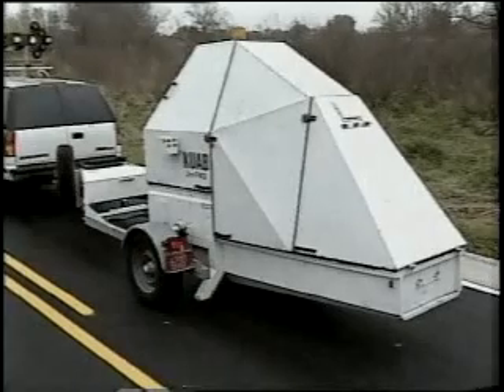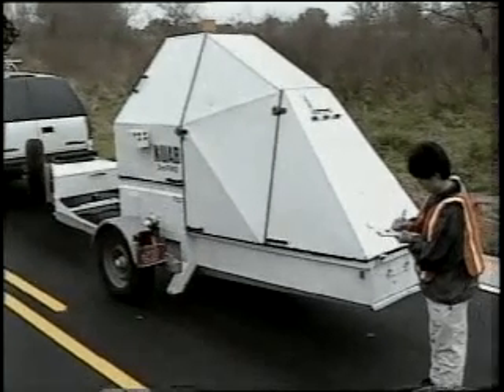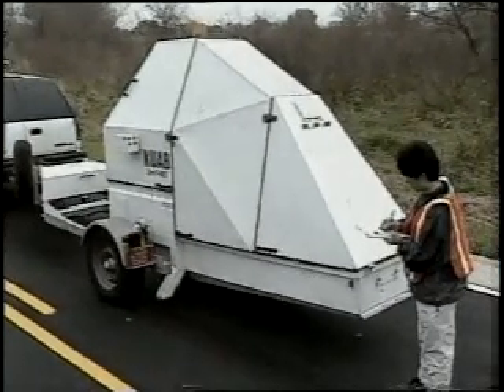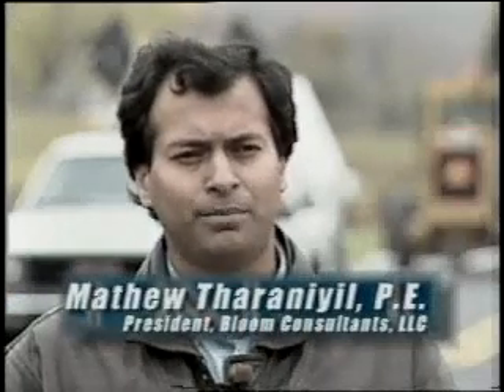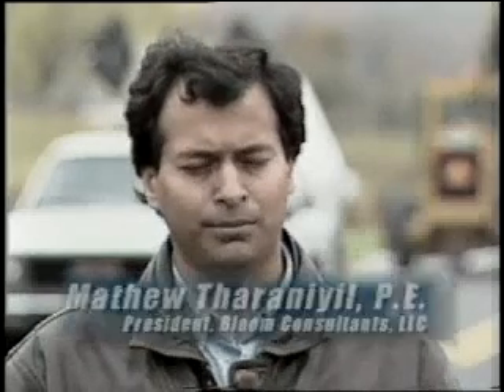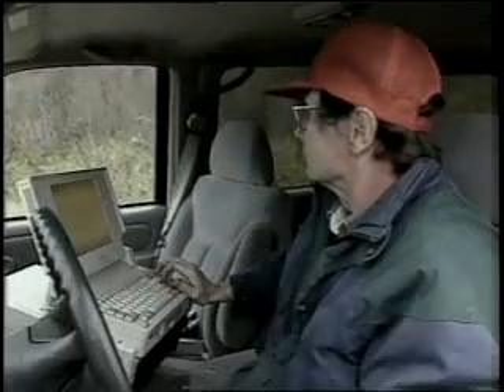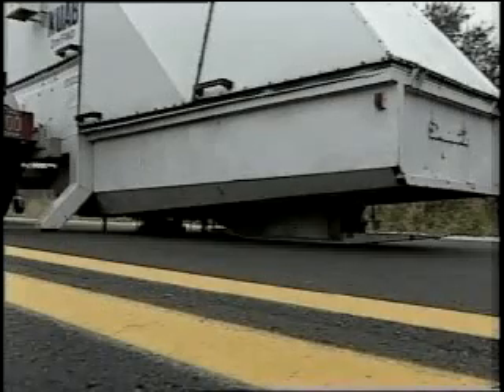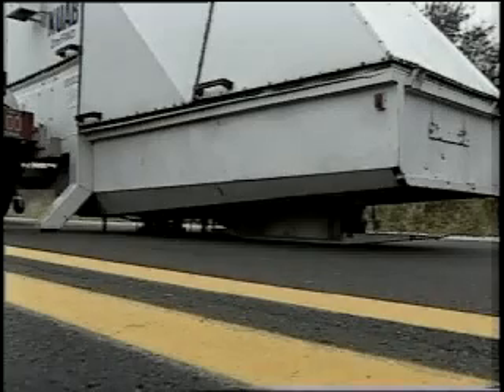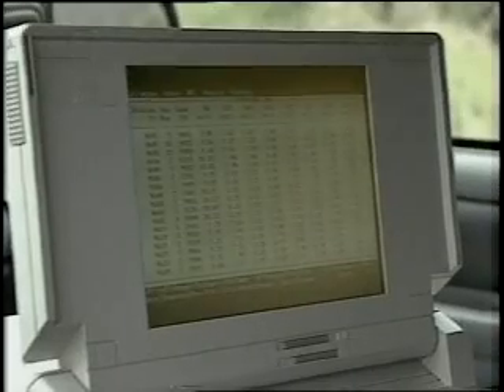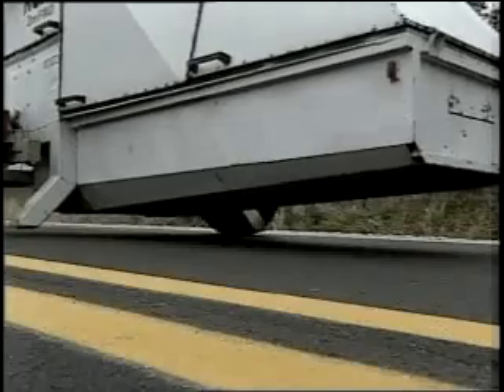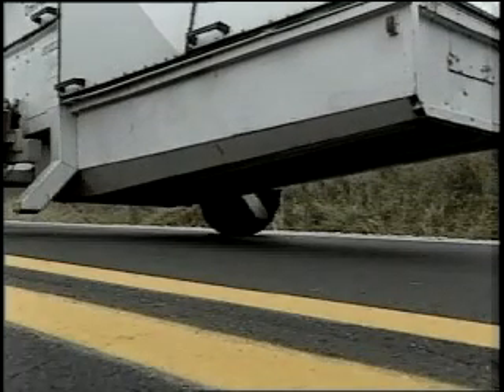In a nutshell, what we do is drop the falling weight on the pavement, and the weight deflects the pavement. And from the deflection basin that's created by the falling weight, there are sensors in the system, in the machinery, that can determine the life of the pavement. What it does is it calculates the deflection of the different layers of the materials that are on the pavement, the base, the subbase, and the surface layer, the asphalt layer of the pavement. And we calculate the structural number and the life expectancy of the pavement.